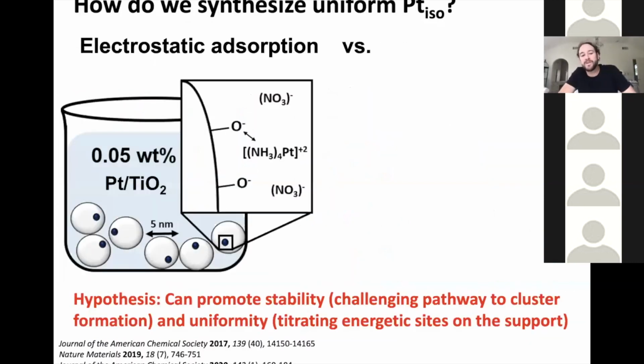So the way that we've adopted trying to make uniform species is relatively simple. We use the electrostatic adsorption of metal precursors onto oxide supports. We do this at extremely low loadings with the hypothesis that the lowest loadings will allow us to titrate the most energetic sites on the support with our metal precursor. And then we try to deposit about 1 metal atom per small oxide particle, so it's very challenging for them to hop together and form a cluster. So this is the general approach that we take.